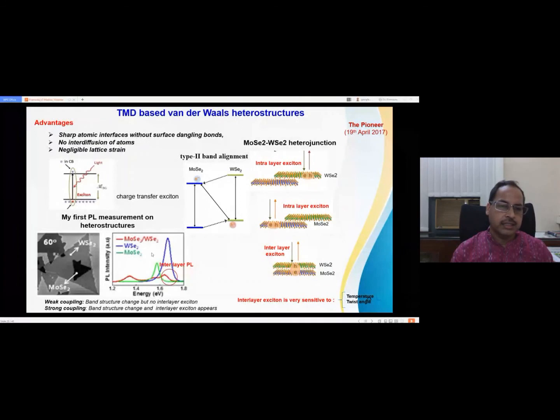So here you can see the WSe2. This is shown in the blue color. This is the MoSe2. When you make the heterostructure in the 60-degree configuration, here you can see there is a transition. There is a large quench in the PL emission, because some of these electron hole pairs contribute in this direction. So there is a quench, and it is obvious, we should expect it. And there is a low energy peak we can see. That is called the interlayer exciton.